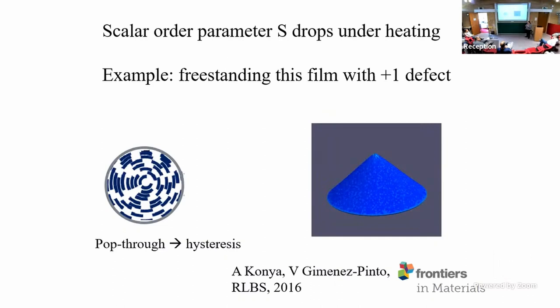We could adapt, yes. So when you say the director associated with each element is constant or something else? It rotates with the body. So here, the orientation of the director is constant, but the scalar order parameter is our control parameter. So when we heat the material, the scalar order parameter drops. Each individual element shrinks along its local nematic director, but the nematic director is defined in the body frame and rotates with the body.